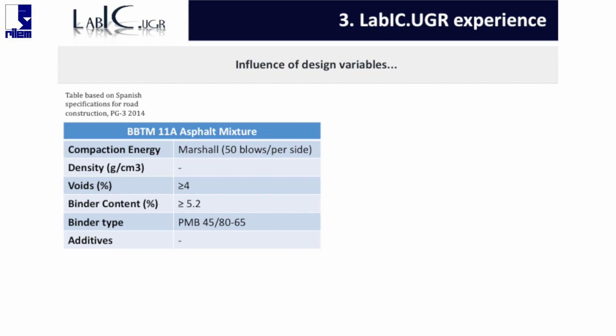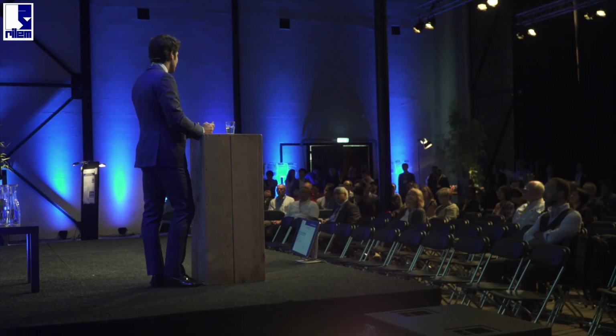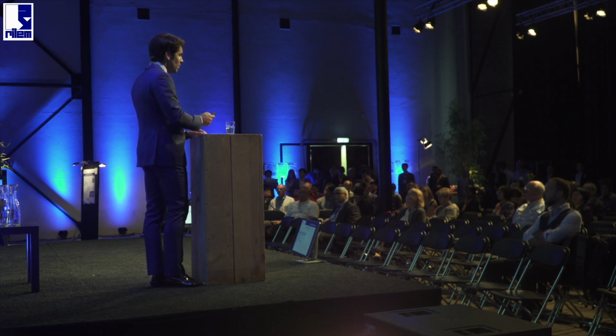It says that the compaction energy must be 50 blows per side in the Marshall compactor. The minimal void content must be 4. The minimal binder content must be 5.2. And the binder to be used should be a polymer modified binder 45/80-65. Okay, if we start to design a material under that criteria, we can apply 50 blows per side, and we